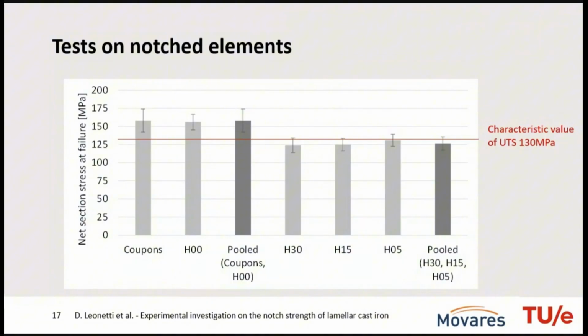But nevertheless, the statistical significance is also negligible, so we decided to pool these data series together, at least for the range of hole dimensions that we examined. It is worth mentioning that if we come up with a characteristic value, so a 5% probability of survival for the ultimate tensile strength, and we applied that as a failure criterion, considering a net section area for the notched specimen, this would not be a successful approach.